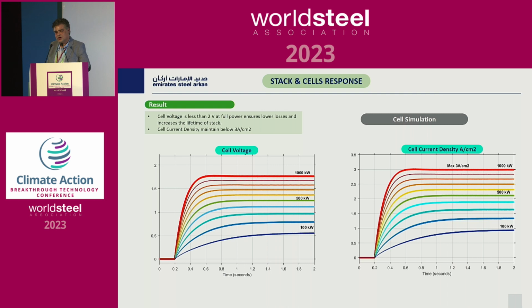Now we go to the stack itself. Why do we focus on the stack? Because if I supply the stack with unstable voltage, the lifetime of the stack will go down. As we can see here on the left side, the stack voltage never exceeds 2 volts, which is the limit, and the current density does not exceed 3 amperes per square centimeter, which ensures the lifetime of the electrolyzer will be prolonged.